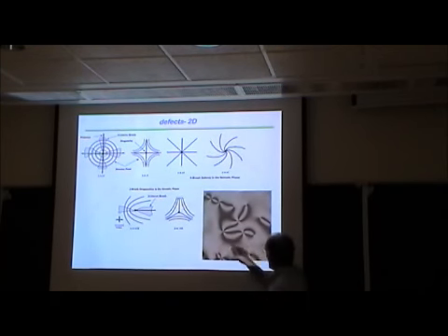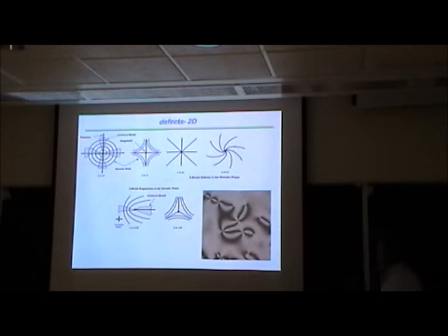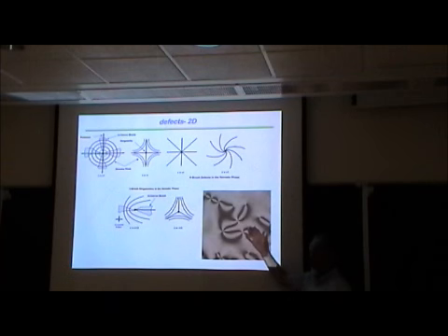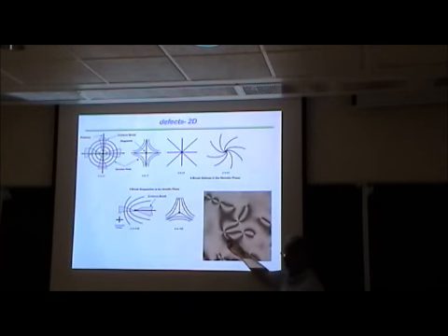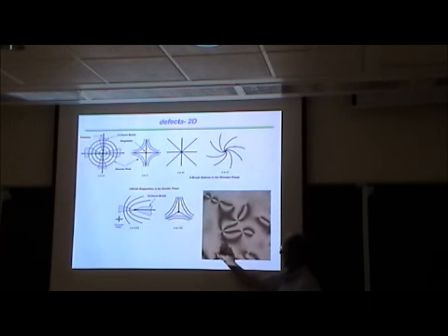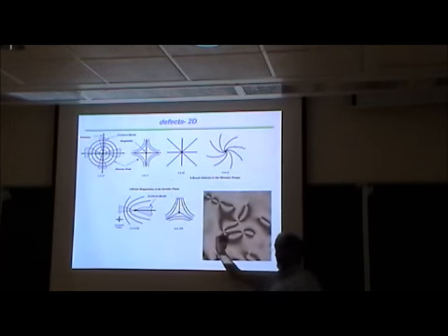The pattern will look the same. So what you do is put into the microscope a plate that just adds birefringence uniformly. If it adds birefringence with the same sign as this, then you'll see the total birefringence increase in this brush and decrease in that brush. So then you can distinguish this orientation from that orientation.